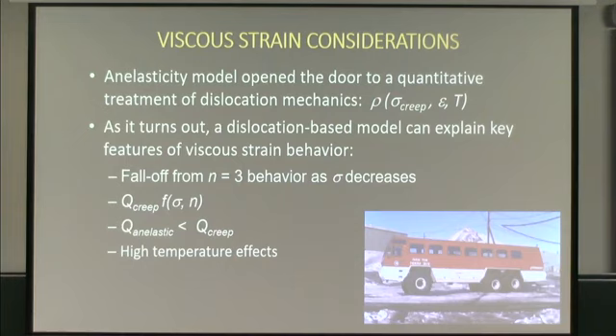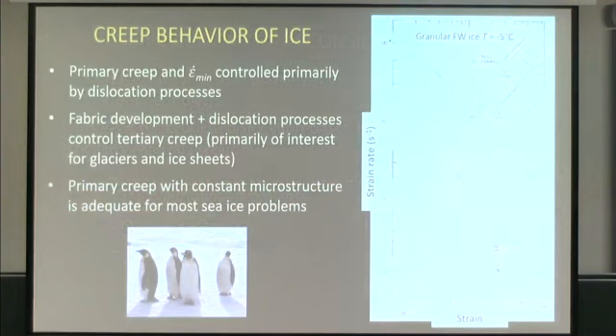It may be 0.1 or 2 or more MPa, in fact, below which you'll have linear viscoelasticity and you'll have linear creep. And then once you exceed a threshold where you're producing a lot of dislocations, you start to see this transition to n equals 3 behavior. The model captures all that, which I think is a pretty cool feature. And that's one of our transportation things down in Antarctica. I have it in the tour bus.